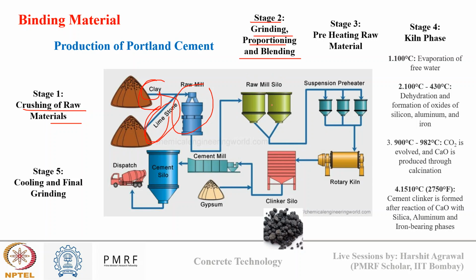Then the third stage is preheating of raw meal. Once this mixture is proportioned, it is preheated using hot gases in a preheater tower. What is the need of this preheater tower? It reduces the energy consumption in the next stage of cement production. So initially the material is just preheated before sending it to the actual heater. Now the fourth stage is the kiln phase. This is the main phase of cement production. The preheated material from stage 3 is heated to a high temperature in the rotary kiln, where all the chemical reactions take place to form the final product, known as clinker.